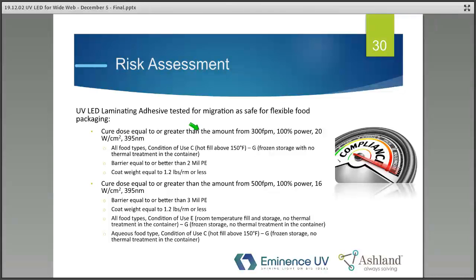One was a cure dose of equal to or greater than 300 feet per minute, 100% power, 20 watts per centimeter squared at 395 nanometers. This passed condition of use C, which is a hot fill condition, and would go all the way down to frozen food storage. This required a 2 mil polyethylene film, linear low density polyethylene. If it were less than that, then we'd have to repeat the test. And here's the coat weight for the material.